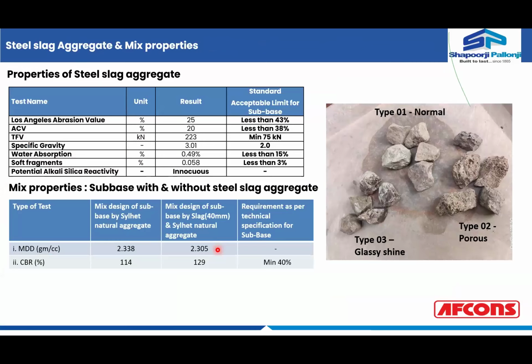Now, what type of aggregates are available, and what were the properties of these steel slags used in this particular project? If you see the properties of the steel slag aggregates itself, the LA value is close to 25%, ACV is 20%, TFV is 223 kilonewtons, specific gravity is close to 3.01, water absorption is 0.49, which is very less, unless you choose a porous aggregate. Soft fragments are less than 3%, and the potential alkali silica reactivity is innocuous.